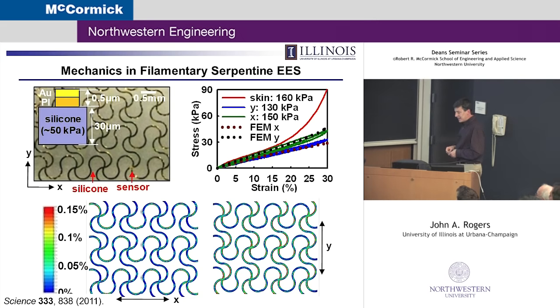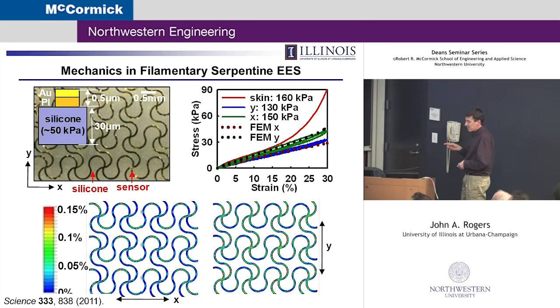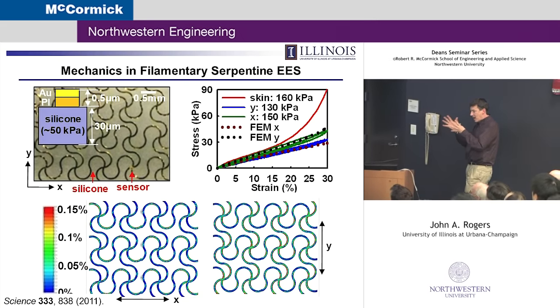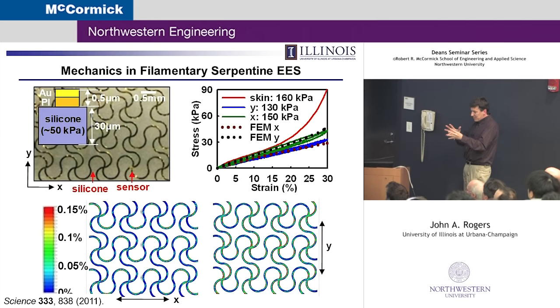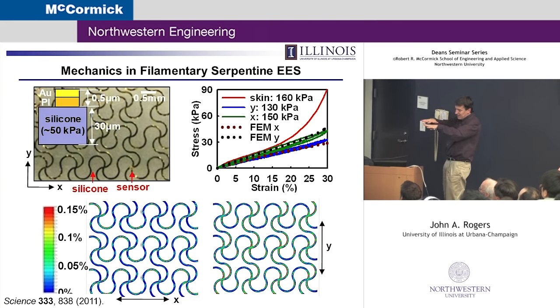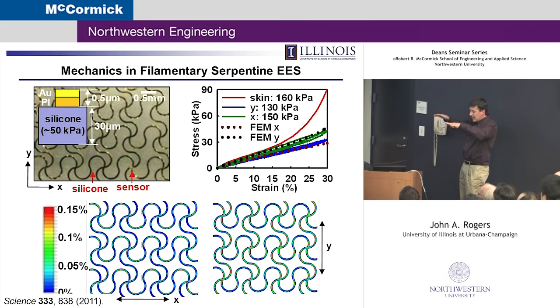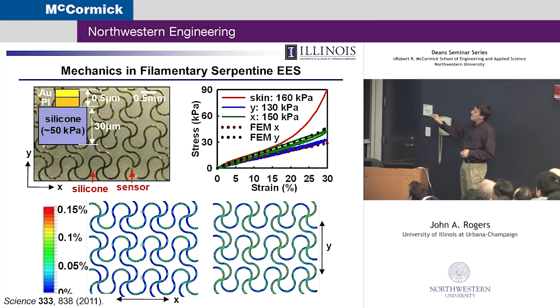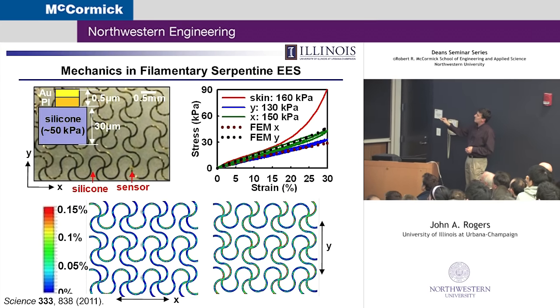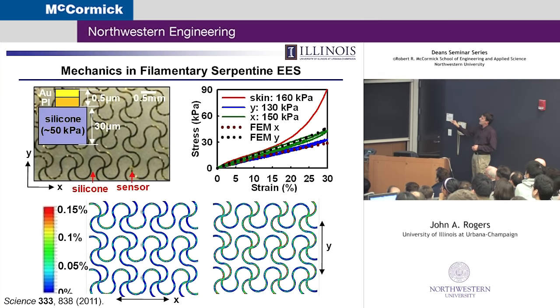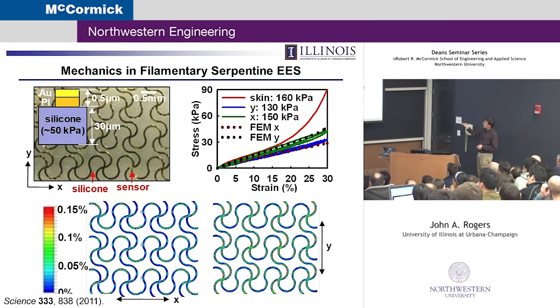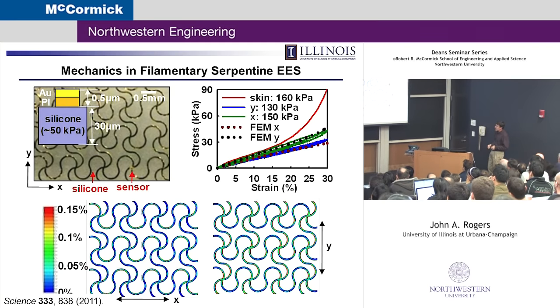Now it turns out that you can basically do that based on what I said before, just a few simple ideas: thin, out-of-plane buckling mechanics, implemented in the way that I showed you, but then with one or two additional elaborations on top of that. Most prominently, taking the integrated circuit, instead of having a sheet that's buckled in 2D, cut it into an open spider web mesh consisting of these very narrow, thin, filamentary serpentines in this kind of layout. Mount that whole thing on a very thin rubber substrate, low modulus, 50 kilopascals, and do all of that with attention to the details of the mechanics.